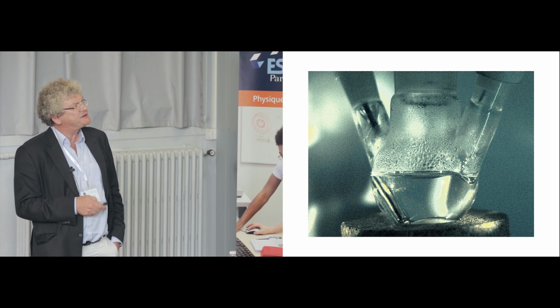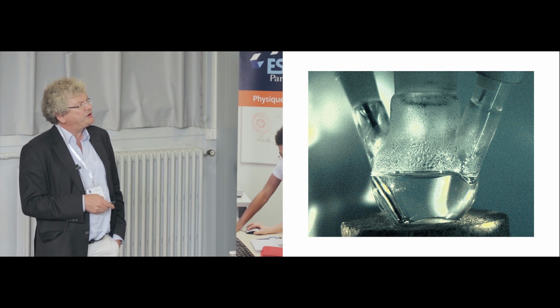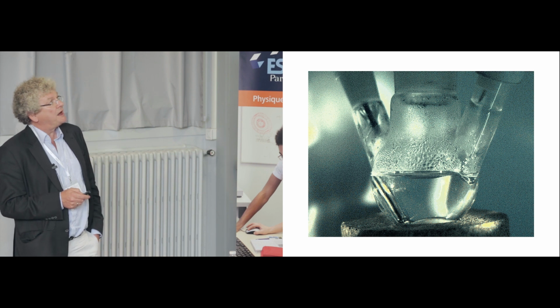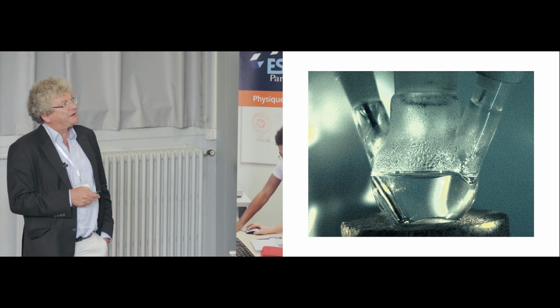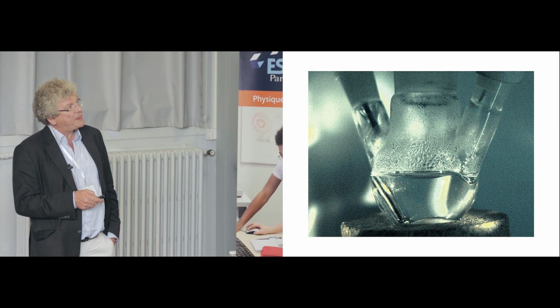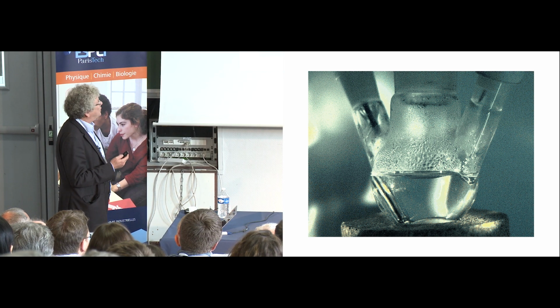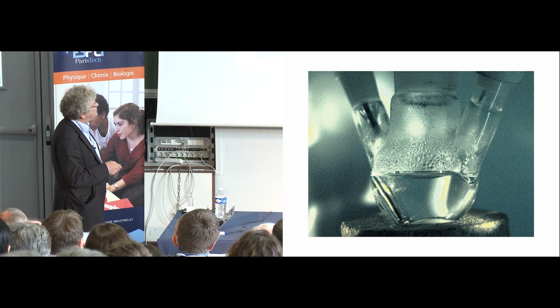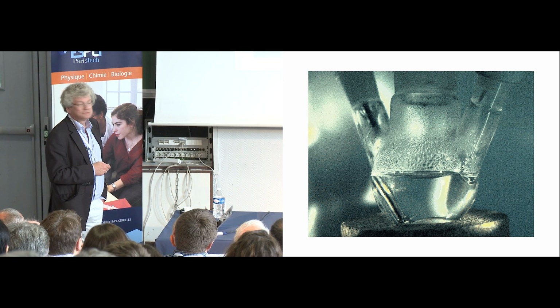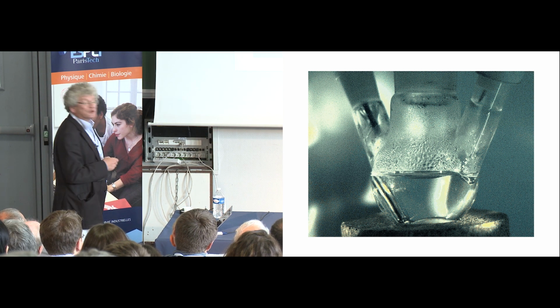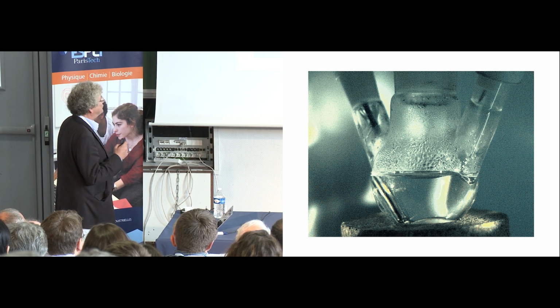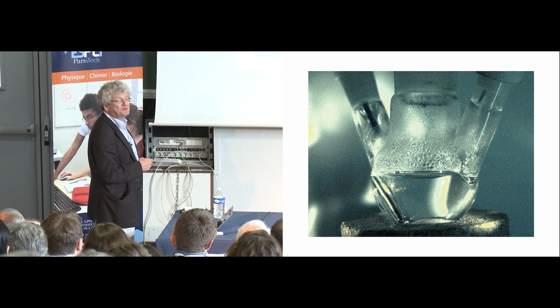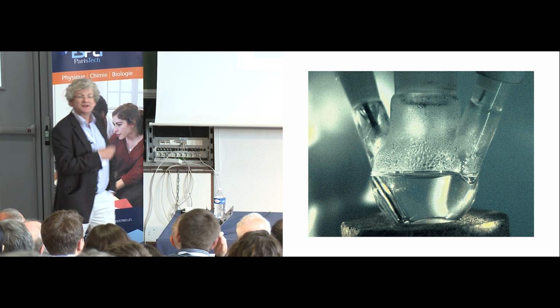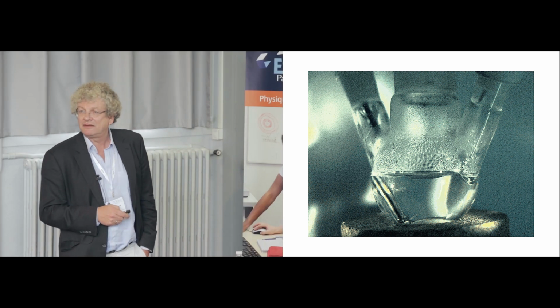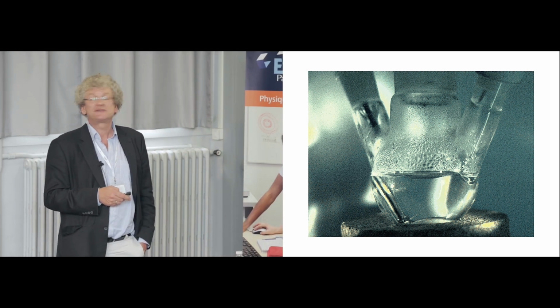Here you can see the synthesis of lead sulfide monitored with a high-speed camera. Now you will see the injection here, and it's getting dark. That means lead sulfide is formed. And you see it's almost quite nice. So almost homogeneously getting black. Beautiful. This is the typical setup, how most people all over the world use it. 50 mL or 100 mL flasks for making these particles.